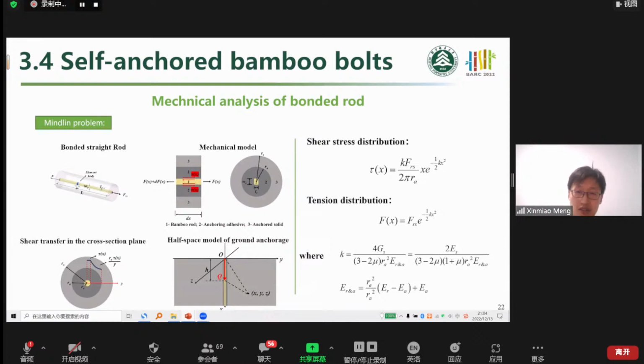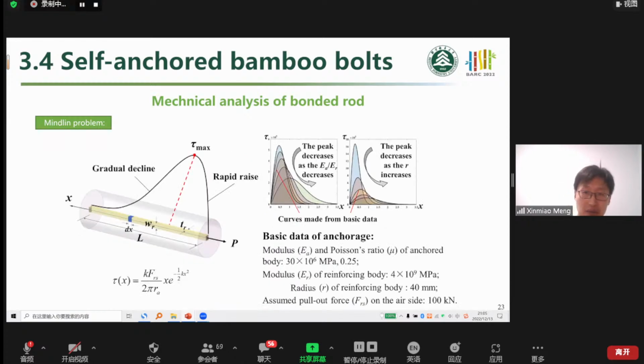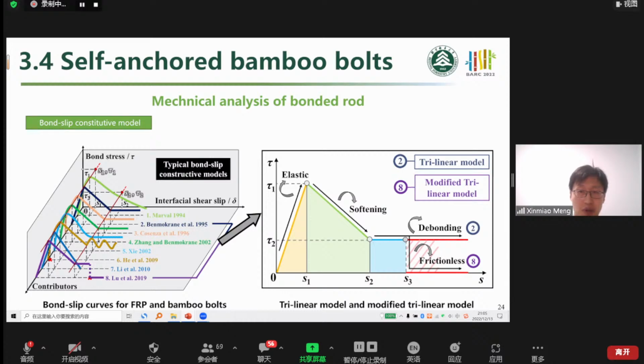We divided the self-anchor composite bolt into two parts. For the linear part, we built a model to predict the shear stress at the interface and the tension force. And we tried two models. This model is based on the half-space model and is based on elasticity. And we can conduct parameter studies to find the relationship between the elastic modulus and the shear stress distributions. Another method is the bond-slip constitutive model. Among these models, we prefer the trilinear model to predict the bearing capacity.